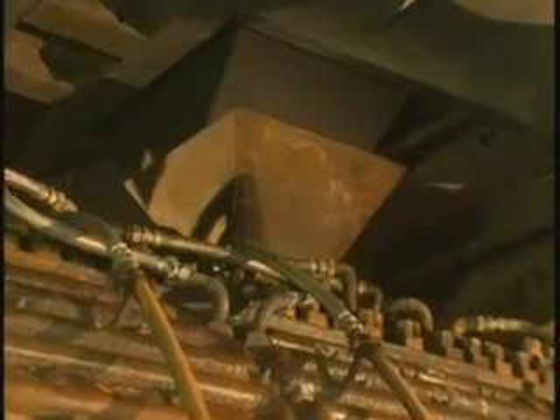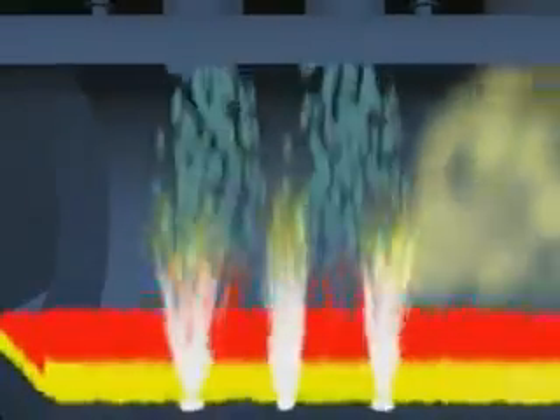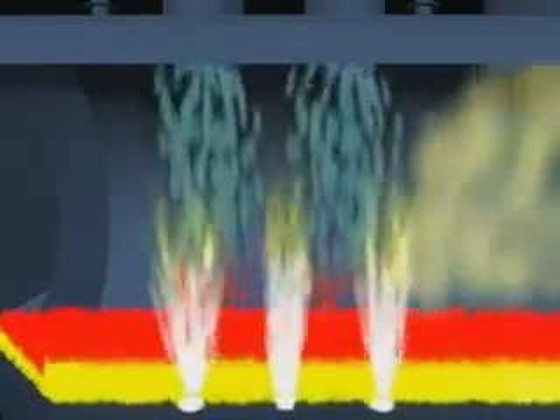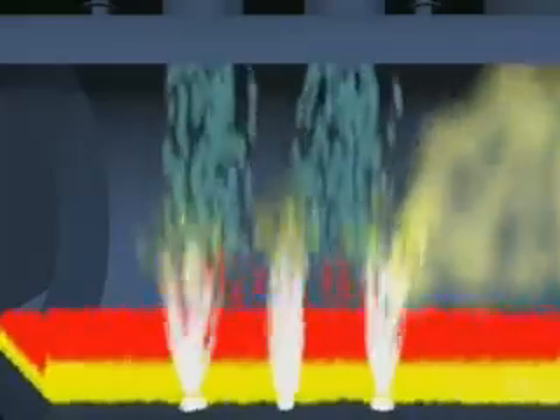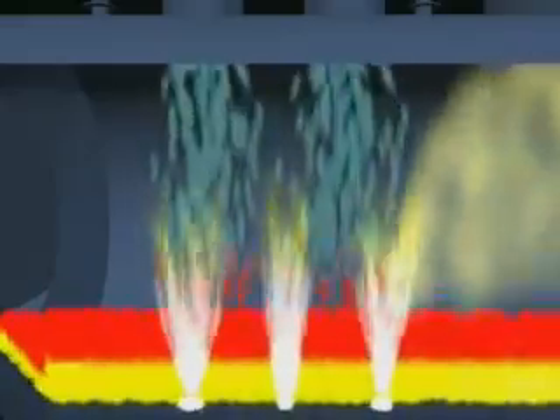In the somewhat thicker oxidization zone, lead ore is dropped into a melt from above. At the same time, oxygen under high pressure is injected from below. The sulfur compounds contained in the ore react violently and become ignited. In this 1200 degrees hot environment, the ore is smelted. The liquid collects at the bottom and flows to the outside through the tap on the right side via a siphon. The entire process works in continuous mode and without interruption.